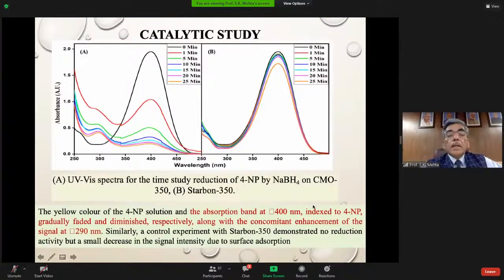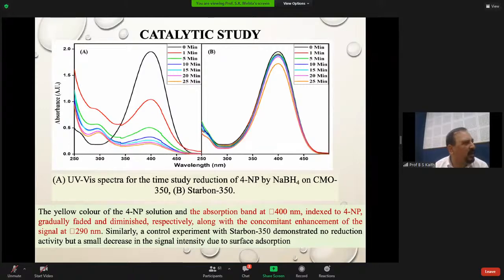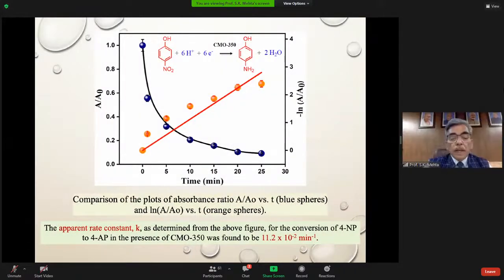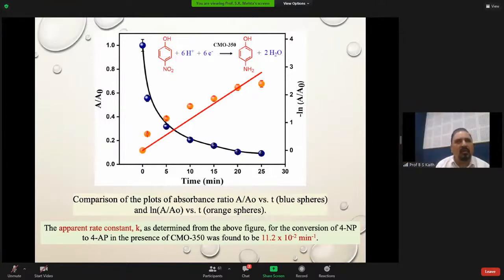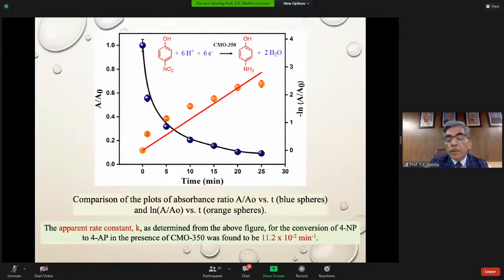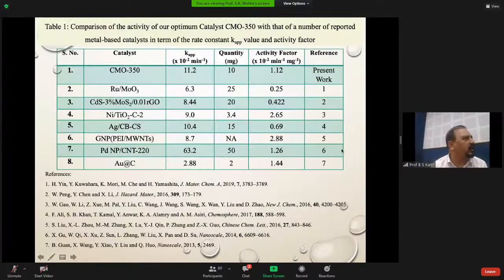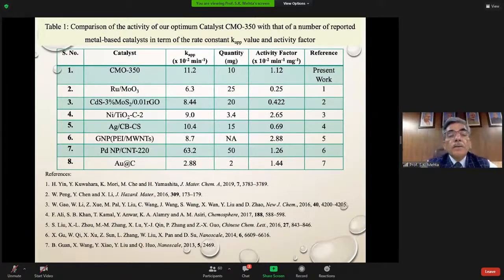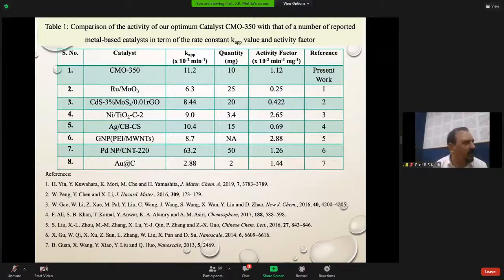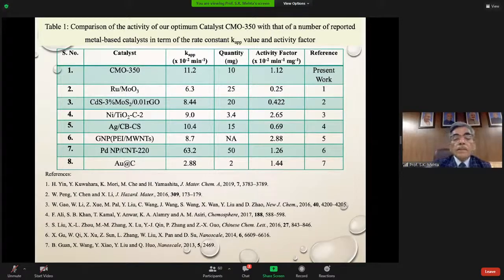So these are the catalytic studies which we did, and we tried to see how much time it takes to complete the conversion. We also tried to find out the apparent rate constant, and we found that it's 11.2. And this is a comparative analysis of our product with the other known ones. As you can see, our rate constant is 11.2, except for 63.2, which is palladium based.